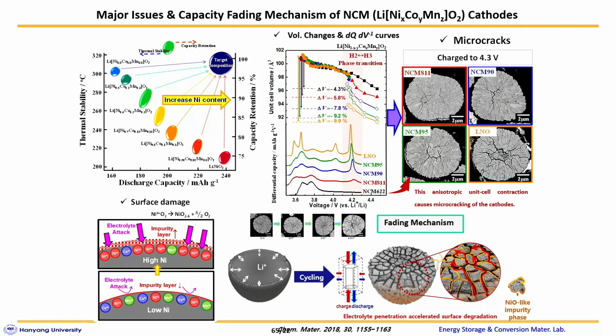This is the capacity fading mechanism. The microcracks formed from the anisotropic volume contraction propagate to the particle outer surface, facilitating electrolyte infiltration along the microcracks into the particle interiors. This accelerates the surface degradation of the inner primary particles by reacting the unstable tetravalent nickel with electrolyte to form a nickel oxide-like impurity phase, and thus gradual capacity fading during cycling.